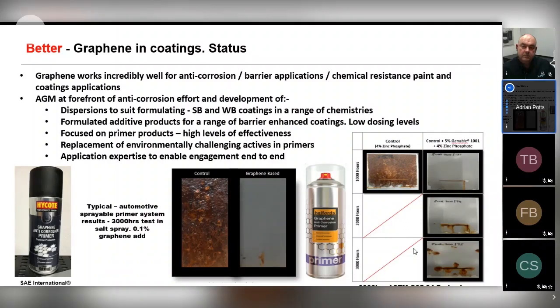I mentioned solvent-borne and waterborne coatings and a range of different chemistries. Typical of what you might expect from a graphene addition to a paint and coating system is seen here in the middle image, the visual image of highly effective corrosion performance for an automotive primer. This is a commercially available automotive primer with a 0.1% solids addition of graphene to that material. So you see this after a 3,000 hour anti-corrosion salt spray test. Image on the left, the current control base material. Image on the right with a 0.1% graphene addition to it.